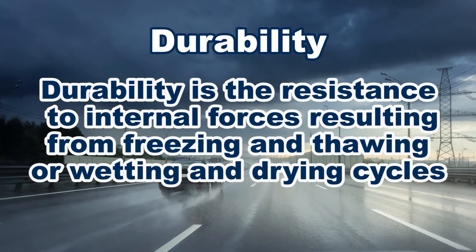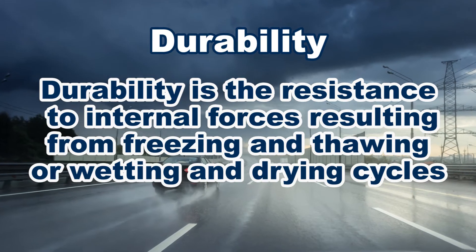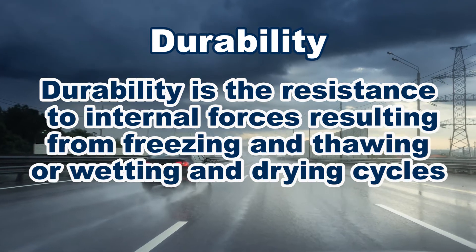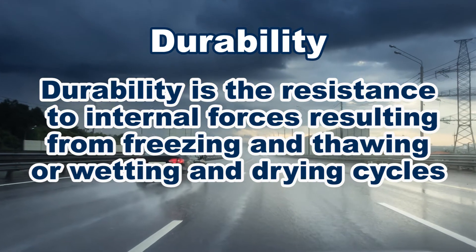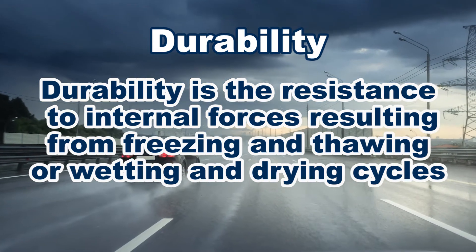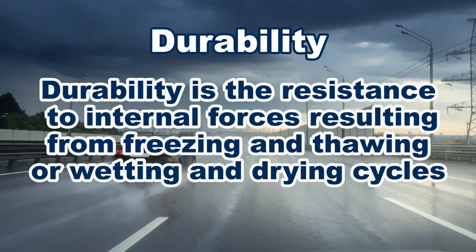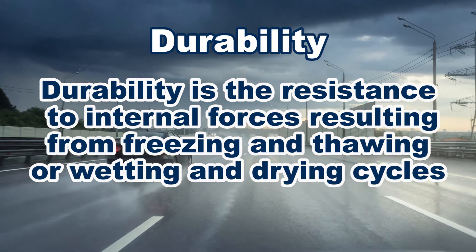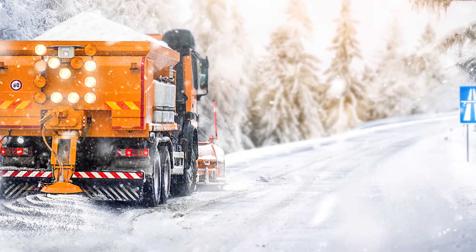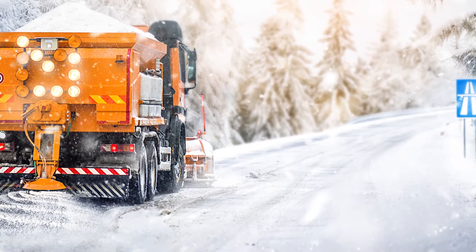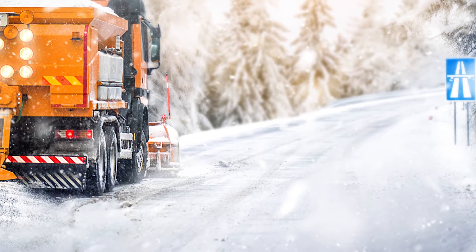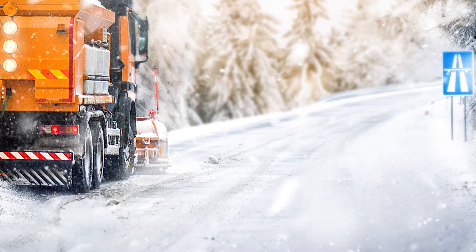Durability is the resistance to internal forces resulting from freezing and thawing or wetting and drying cycles. Expansive forces generated in voids and fissures can lead to disintegration of aggregate particles.